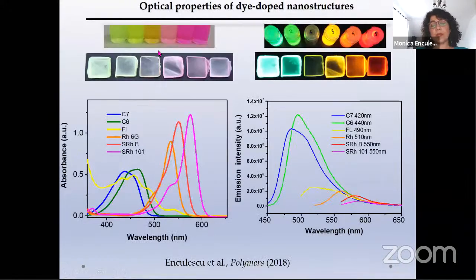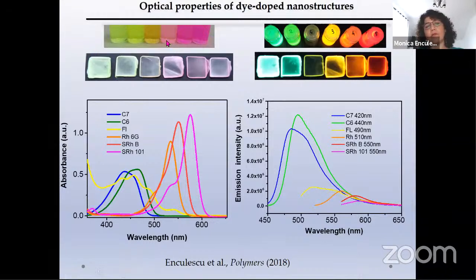And what we had was covering the entire domain with this type of emissions from the blue to the red by electrospinning different dye-doped polymers. So polymer actually doped with different dyes that have different type of emission that are actually covering the entire visible domain of the spectra. So we have different efficiency, so it's not so simple to mix them and to produce white light, because depending on the light that we want to produce, bluish, reddish, we have to change the composition in our type of nanostructures, the composition and the concentration of each dye in our nanostructure.